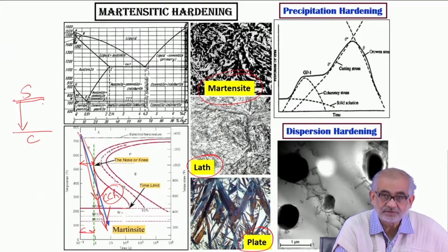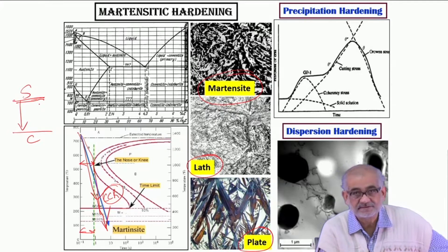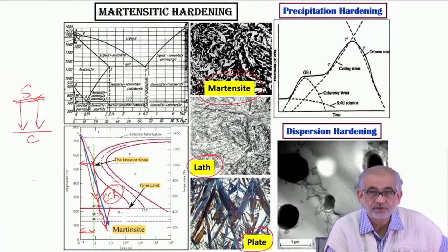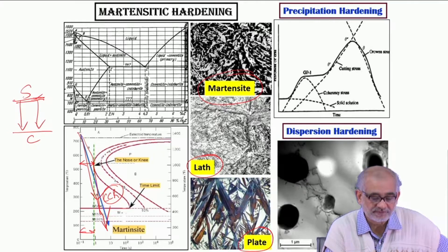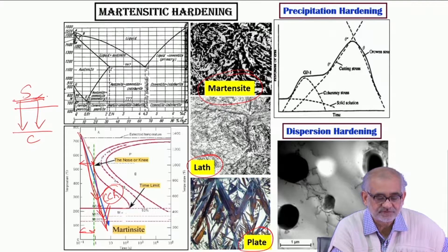The cooling rate also - whatever temperature we expose - is of course highest at the surface. When we quench, the cooling rate will be highest at the surface and also decreases as we go deeper into the interior. In fact the cooling rate that we ensure is actually applicable up to a certain depth from the surface and not beyond.